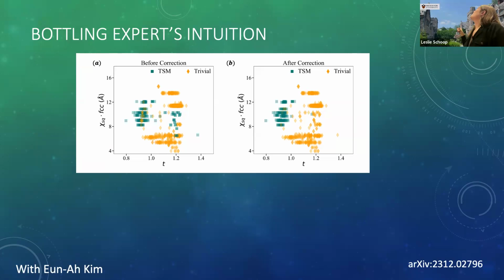What we did then is look more carefully at those materials that are kind of messy here in our data set. Those were all materials where there wasn't any experimental input. We ran more DFT, and more hybrid DFT calculations, to confirm the band structure. And we saw that some of these labels were placed incorrectly. When we relabeled, we saw that it actually separated super well with these methods.